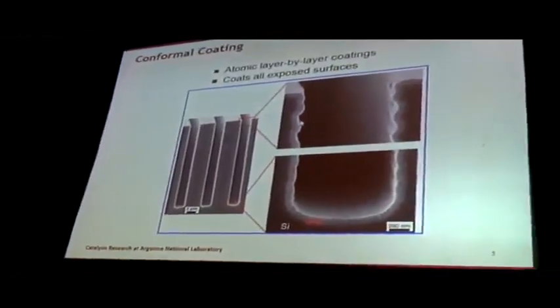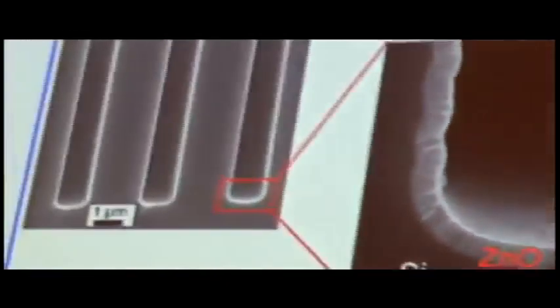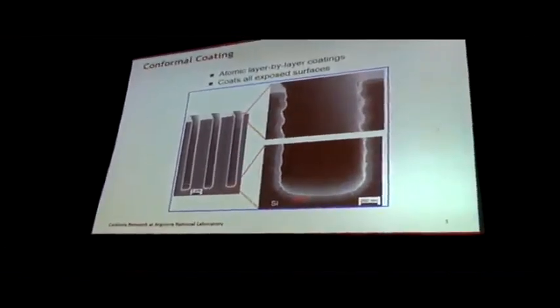Okay, here you see some very deep wells, in which this is zinc oxide that is going down onto the surface of the catalyst. And you can see in the upper portion that even the little dimples that show up in there do line. So there are no pores that are going to be non-accessible to this. So we can really probe into the pores of things like zeolites, deep into large particles, etc. So it coats everything.